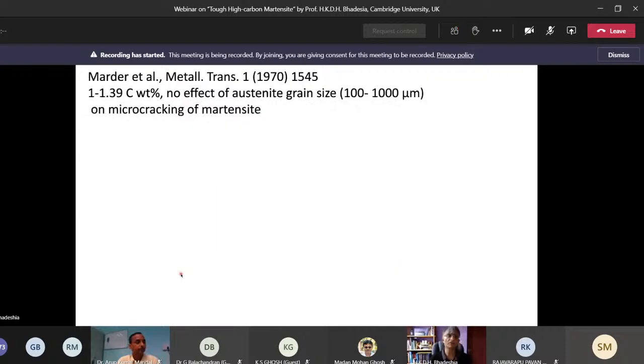But let's examine this in a bit more detail by looking at literature, which was published many decades ago. There's a classic paper by Marder and Krauss and colleagues from 1970, looking at steels containing up to 1.4 weight% carbon. What they found was that all the plates are microscopically cracked when you quench this material, and that the austenite grain size in the range about 100 micrometers to 1,000 micrometers doesn't make any difference. They all exhibited microscopic cracking.